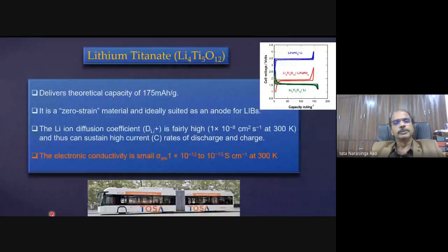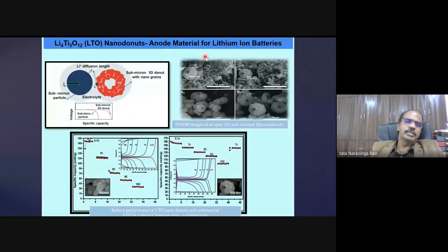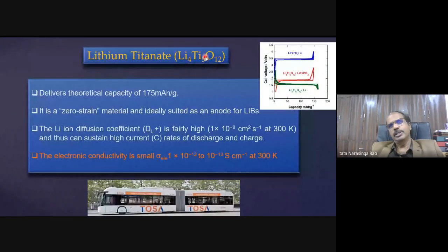That's what we do. And the other material, lithium titanate, I told you, which is an anode for fast charging. That is also the same thing, because again, it is not such a good conductor. So we have to make it in nano size. So what I am showing is that nano size makes a difference. And the Nobel Prize that Goodenough got, because of LiFePO4, is really seen in electric vehicles, because they are converted into nano size and carbon coated. And the size has a big thing to do, and nanomaterials have a big contribution in energy storage in electric vehicle